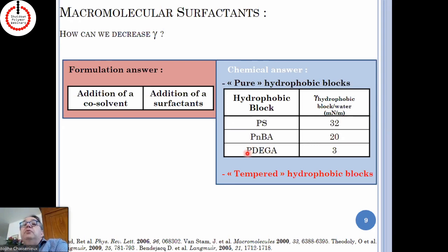But if you now go to polymers with a much lower surface tension, for instance all that we know about derivatives of ethyl acrylate, you can see that we have systems with a very low surface tension that will show equilibrium properties, and self-assembly driven no longer by the preparation path that you follow to make them, but much more by thermodynamics.